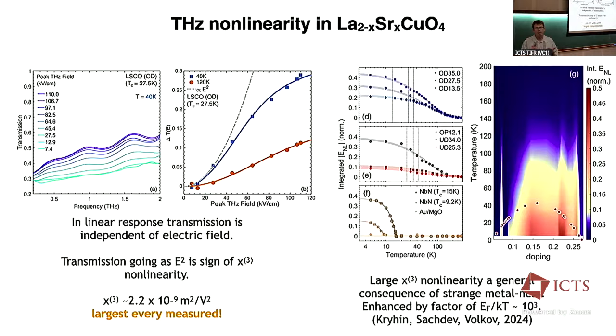They're still strong by any standard. We've done experiments, and in fact you can see here, we did experiments on niobium nitride and gold films. Niobium nitride shows large nonlinearity in the superconducting state, and then it's just flat in the normal state. That's niobium nitride, flat, and that's gold. That's a conventional Fermi liquid, and it shows no nonlinearity that we can measure at all. So overdoped cuprates are less interacting, but still strongly interacting by some standard.